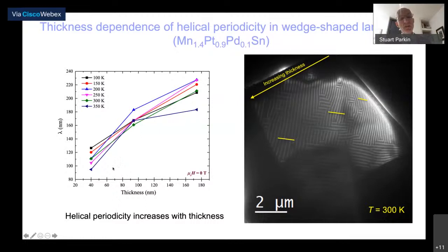And it turns out that the period shown on the left of this helix is increasing by more than a factor of 2 as we increase the thickness of this lamella from 40 nanometers to 180 nanometers. This was quite a surprise because to date, in no other system had such a strong variation of the size of the helix, and I'm going to show you in the next foil of the antiskyrmion varied in this dramatic way.